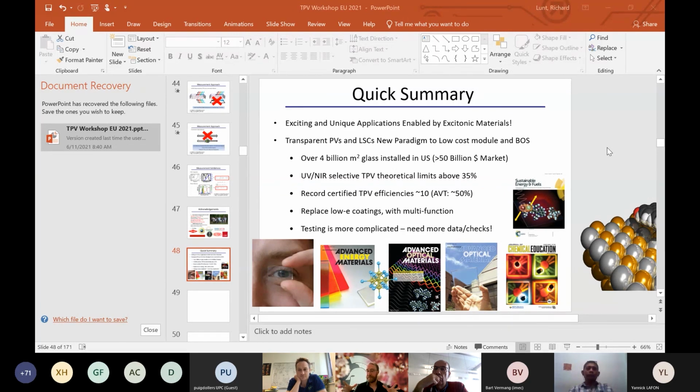We are already making foot by foot modules on the solar concentrators. At the same time, on the PV side, I think you have to recognize that there are scaling losses to charge transport. Whatever your lab scale is, you're going to lose a bit going into the module, and rule of thumb, you lose about 25%.